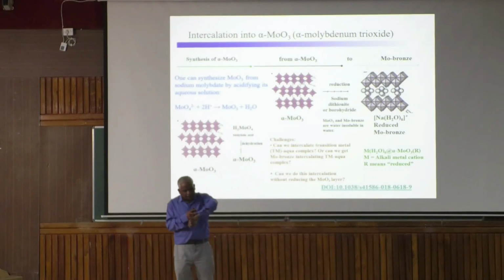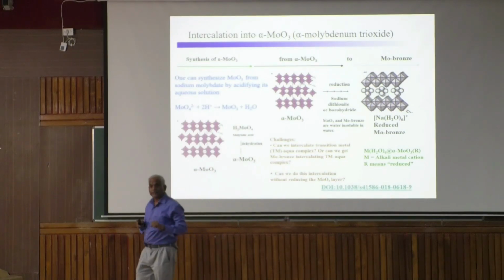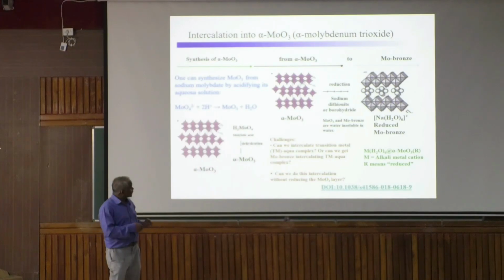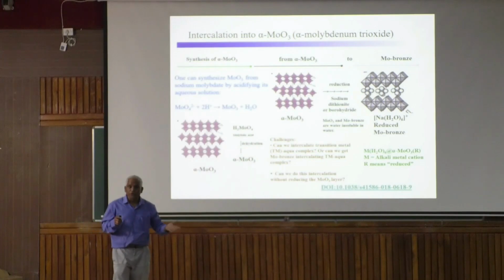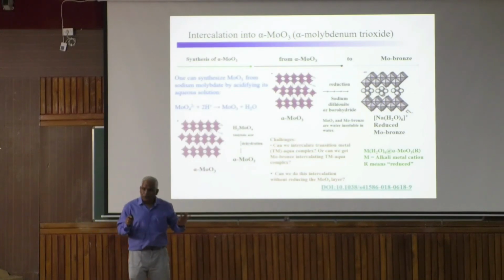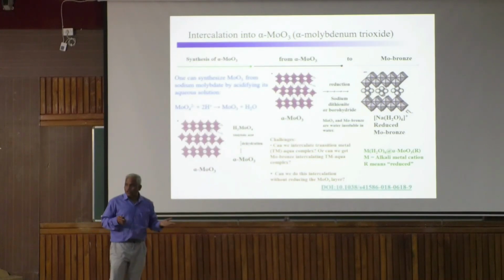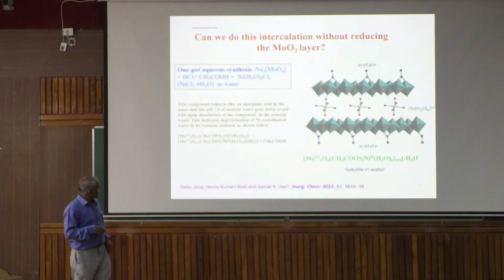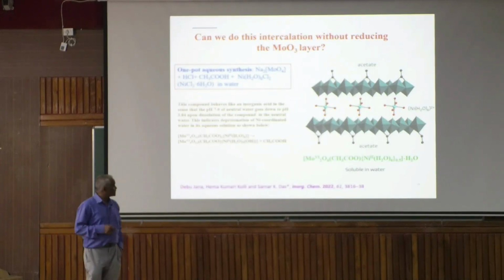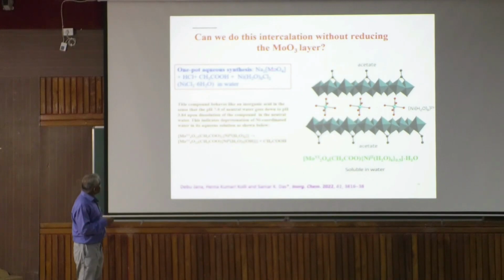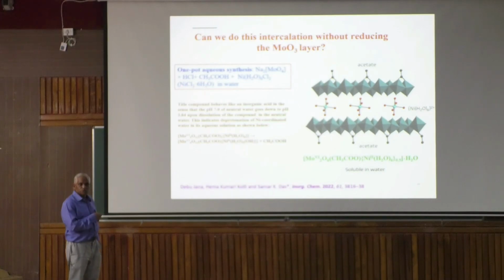Although it was discovered more than 100 years ago, in 1896, and alkali metal aqua compounds are known, a transition metal compound, like copper or cobalt or nickel, was not known. There we could contribute. We were lucky enough. Why it was not known, we did not know. We could get that again by single crystal crystallography. For the MSc lab practical, the same thing we use: sodium molybdate, HCl, we use acetic acid and we use nickel. Although I write it like that, it is actually nickel chloride 6H2O. If you look at the formula on the bottle in any lab, it is nickel chloride dot 6H2O.